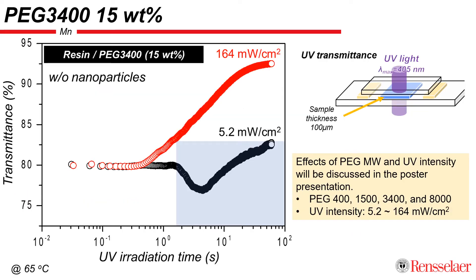This is the relative UV transmittance of polyethylene glycol 3400 molecular weight containing resin. UV transmittance was measured on the resin in a confined thickness of 100 µm under UV light at 405 nm over time.